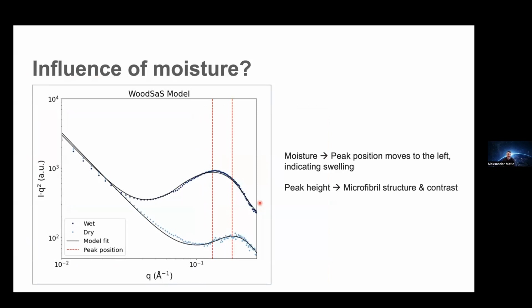Here is how it could look, for instance, one example of a result that Linnea got when comparing wet and dry samples. In this particular experiment, they didn't have the humidity chamber ready yet. So here the samples were just wet and dry, and then taken. The wet sample was taken out and put on the beamline and measured as soon as possible. So it's maybe drying a little bit during the measurement. But what you clearly can see is that the two SAX patterns differ a lot. The most pronounced thing is that this peak here shifts to lower Qs, which indicates that we have some kind of increased distance. So we have some kind of swelling, and we'll see later that this is then related to changes in the microfibril structure.